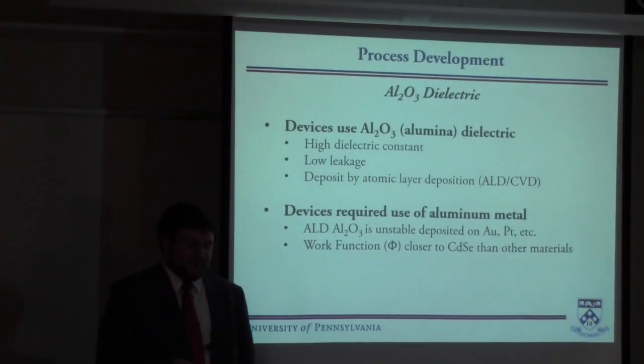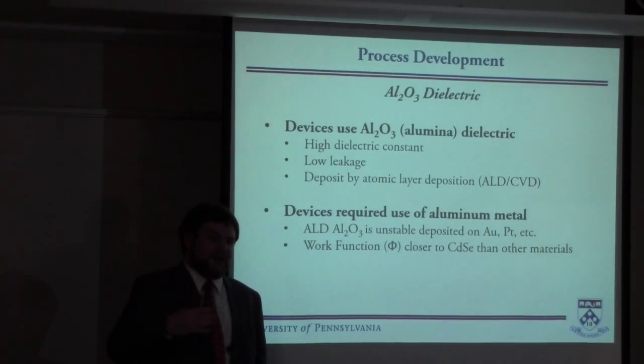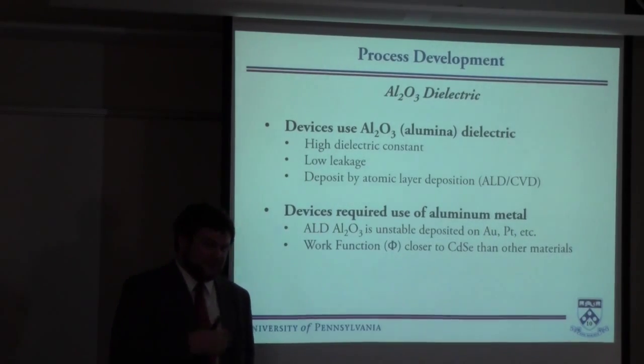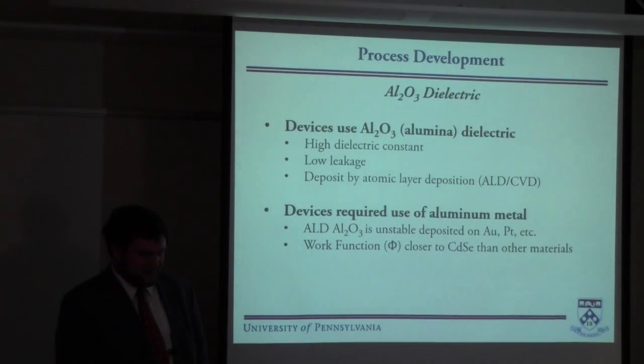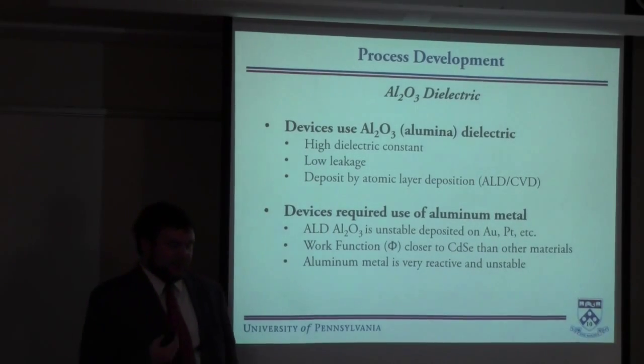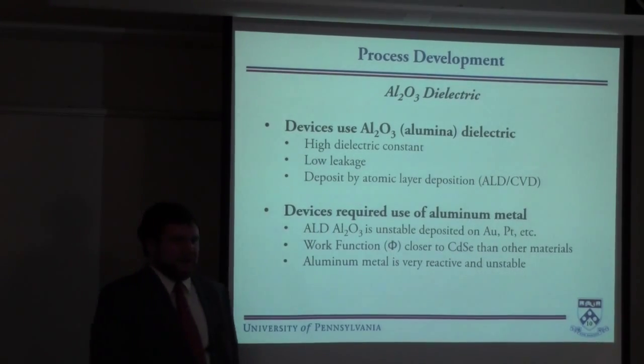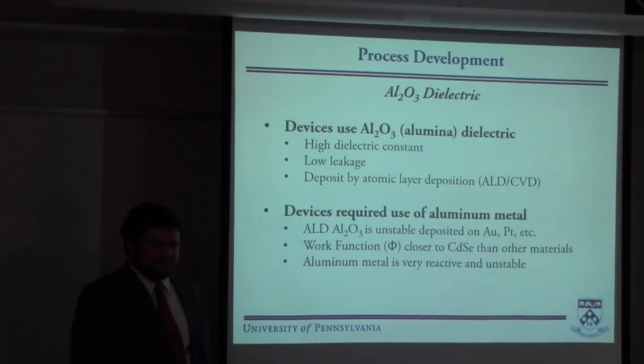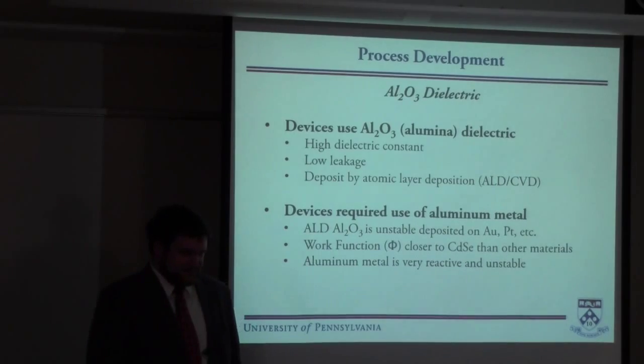The other benefit of aluminum is that the work function's closer to that of CdSe. So then we're decreasing our threshold voltages and keeping a low voltage operation, which is what we're focused on. But aluminum metal is very reactive. It's not very stable. It tends to like to form oxides very quickly, and it just isn't very nice to work with.